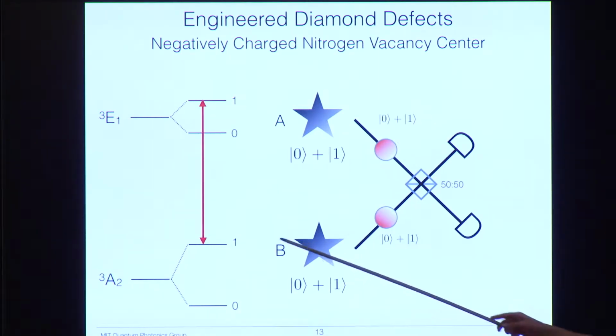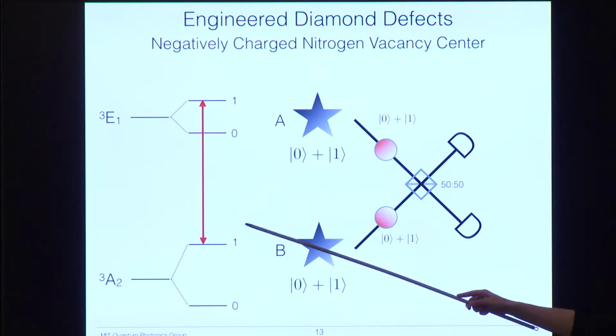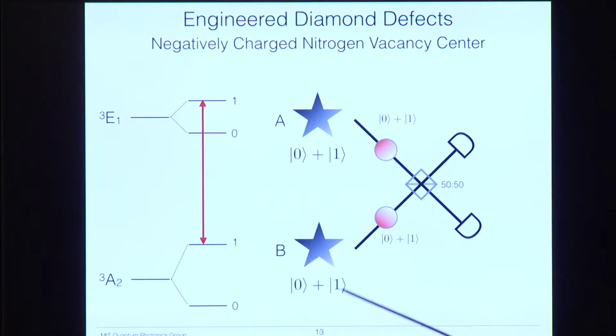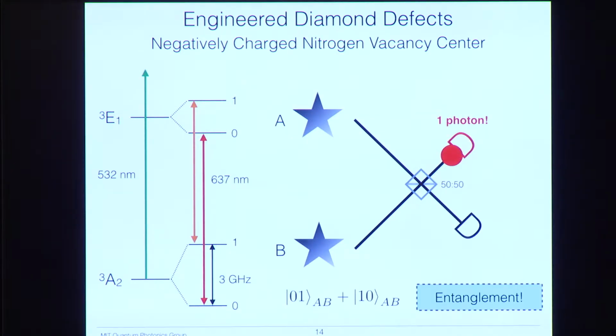We then excite only one of the transitions, and that moves the superposition of the spin state into a superposition of the occupation of a photon mode for both channels coming from each NV center. Then we put these two optical modes on a beam splitter. This erases any information that we had about the origin of the photon. So if we get a click that says we only have one photon, we don't know which one it has come from, so we have created a fully entangled state between NVA and NVB. And there are some tricks that we can play to make this more immune to loss and noise, but that's the basic idea.